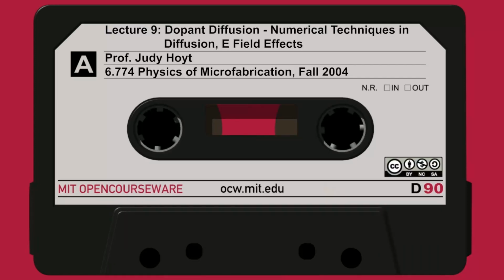So we can substitute in for the mobility in the upper right hand equation with q over kT times D. We can also substitute in the fact that the electric field E is the gradient of the potential, where the potential psi can be related to the carrier concentration n as minus kT over q times the ln of n over n_i. So basically, by substituting in the expression proportional to diffusivity for mu, and substituting in for the electric field, how it relates to the potential, and therefore to n over n_i, we get the equation near the bottom for the flux F.